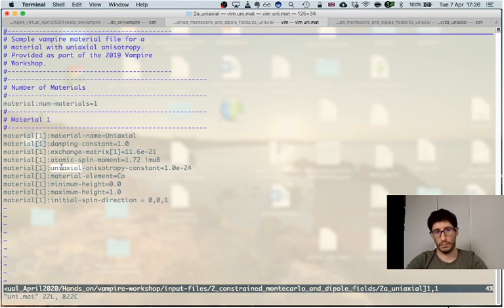What is interesting looking at the anisotropy, again, we want to run a uniaxial anisotropy system. So we have a uniaxial anisotropy constant, which sets the anisotropy to be along the z direction. We set the name, the element cobalt, which can be used when we render the configuration file with programs such as Rasmol, and then we set the simulation to have just the whole space occupied by the system, and we initialize the spin to be along that.